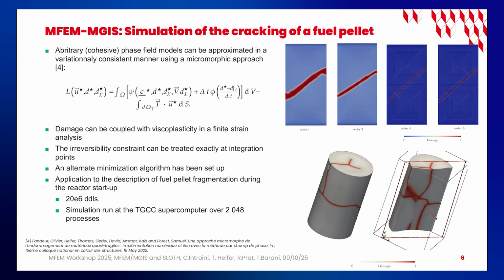And also, we have to mention that the crack propagation is unstable and that you have to break the initial axisymmetrical mechanical field to localize the damage into those cracks, which is quite difficult to do. And we were quite happy with the alternate minimization algorithm that we have set up because we were able to describe this complex crack network, which appears in quite an unstable manner.